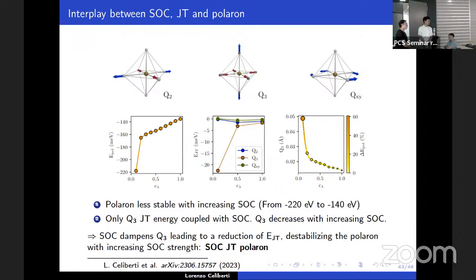Is the magnetic transition at 7 K? Yes, 7 K, from ferromagnetic to this canted antiferromagnetic. Is there any structural deformation by octahedron rotation or octahedron tilting? So tilting, it seems there is no footprint of tilting, but when you have this transition at 11 K, you have orthorhombic distortions. Basically this one. And our calculation shows that there is also a component with this symmetry and a component with this symmetry, because these are independent modes, and you can have something resulting from the mixing of these kinds of distortions. But the leading one seems to be the orthorhombic one, the pristine.